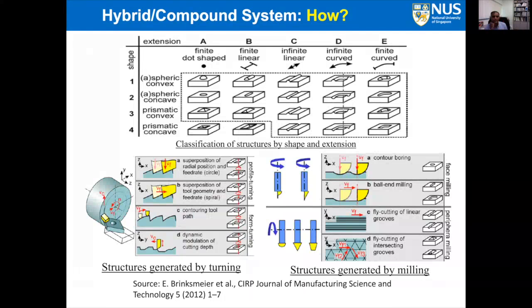These can be generated by the turning process, as shown below on the left hand side. By using the turning process, you can produce very interesting shapes using profile turning. We can also use form turning to produce interesting features. We also do face milling to make spherical or aspherical concave and convex surfaces. We also use fly cutting or peripheral milling to produce micro grooves or intersections of micro grooves in order to create prisms or any other features associated with that.